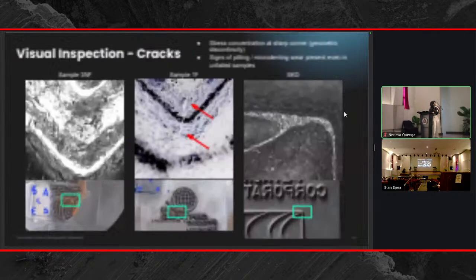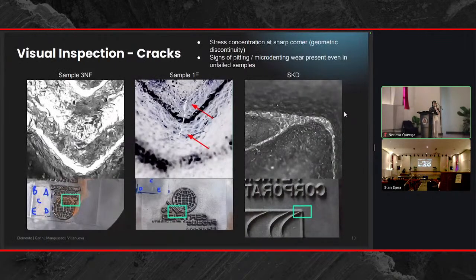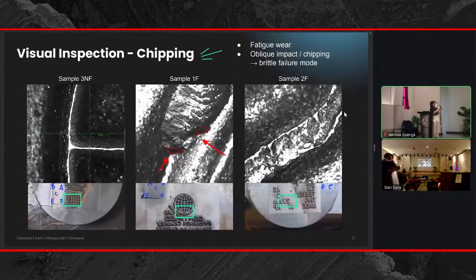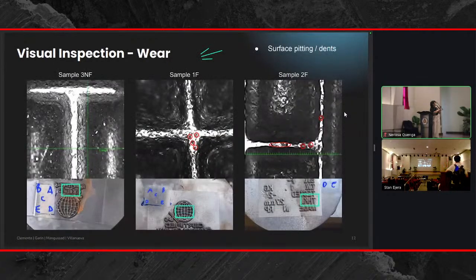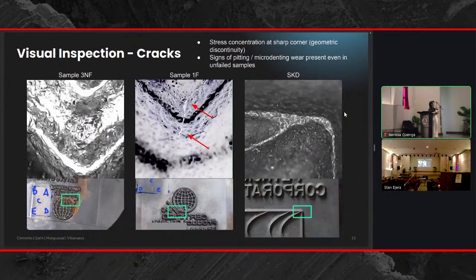Chipping here was shown usually on curved edges. We have the oblique impacts here showing a brittle failure mode, and wear was found in all samples, but notably higher in concentration for the failed samples here. Wear is inevitable, but if gathered in enough concentration, it also can lead to effects such as the letters not being embedded properly during use. Chipping was only found in one instance here in the check mark for sample 1F. This is likely due to the stress concentration at this sharp corner here.